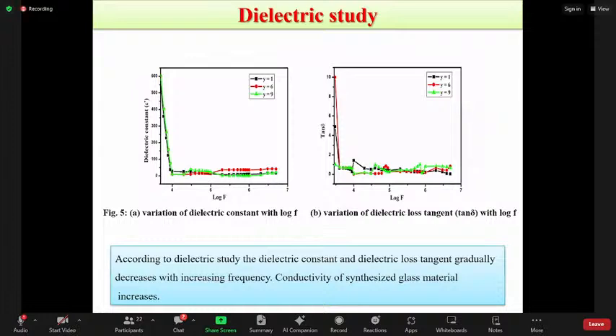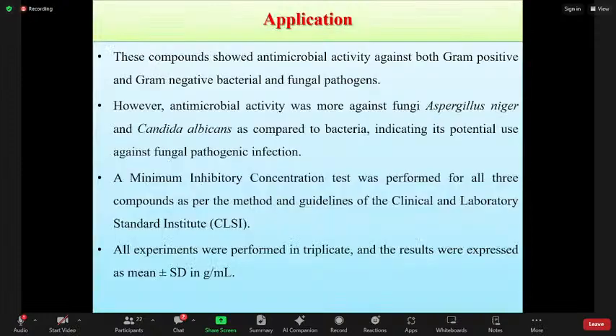According to the dielectric study, the dielectric constant and dielectric loss tangent gradually decrease with increasing frequency, and the conductivity of the synthesized glass material increases as the doping of TeO2 concentration increases. Then we see the antimicrobial activity. These compounds show antimicrobial activity against both gram-positive and gram-negative bacterial and fungal pathogens. However, the antimicrobial activity was greater against the fungi Aspergillus niger and Candida albicans as compared to bacteria, indicating its potential use against fungal pathogenic infection.